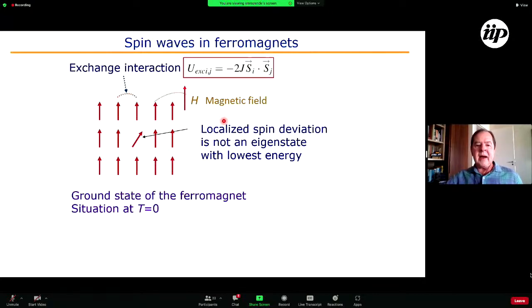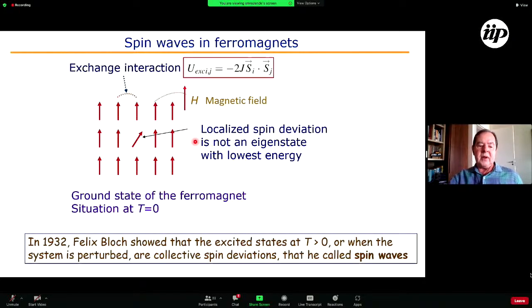In the model of Weiss, the excited states were localized spin deviations. It turns out that this is not an eigenstate of the Hamiltonian, and this was shown by Felix Bloch in 1932, that the states at higher temperature, in other words, the excited states, are not localized spin deviations, but they are collective modes. These collective modes he called spin waves.